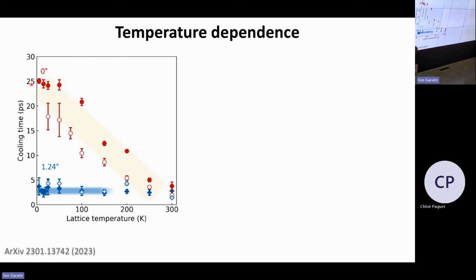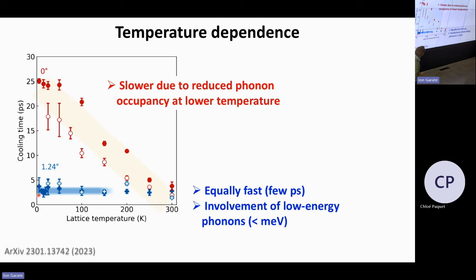Now, in the case of the twisted bilayer graphene near the magic angle, that doesn't happen at all. So it's equally fast at room temperature as it is at even 10 Kelvin. So this already tells you that probably there's some involvement of phonons with very low energy, because even down to 10 Kelvin, you're not affected at all by a lower population of your phonons. So there must be low energy phonons involved. That's what I'm saying here.